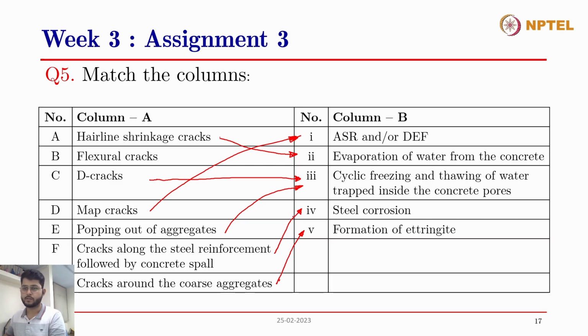And you can just do a simple test, preparing specimens for the initial setting time and final setting time tests. I have done it in my lab as well. When you're doing this Vicat apparatus test for setting time of cement, when you cover the samples from outside and do not let the water evaporate, and compare with the samples you do not cover, you'll see that these hairline cracks appear on the samples that are not covered, because the water is getting evaporated. Sometimes we confuse the evaporation of water for the cement having already set, but it is just evaporation of water, essentially the drying process and not the setting due to the hydration process. So these hairline shrinkage cracks can appear due to the evaporation of water.